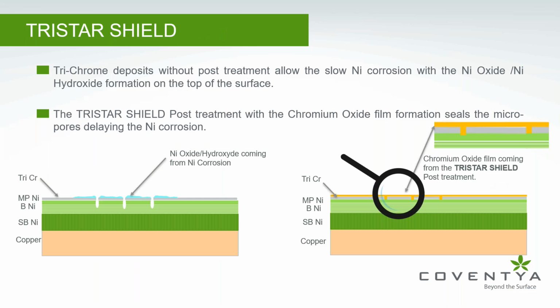Well, trivalent chromium plating cannot create a protective oxide film like hexavalent chromium. In fact, the layer of the deposit with no post-treatment allows low nickel corrosion with the formation of oxide on the top of the surface. Only the combination of Tristar 330AF and Tristar Shield creates an oxide film formation, sealing the micropores and retarding the nickel corrosion.